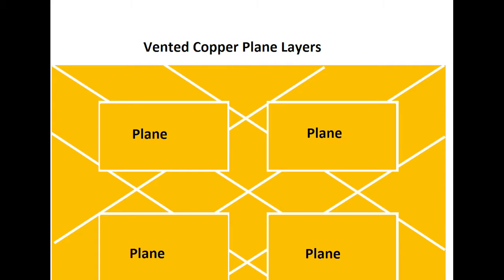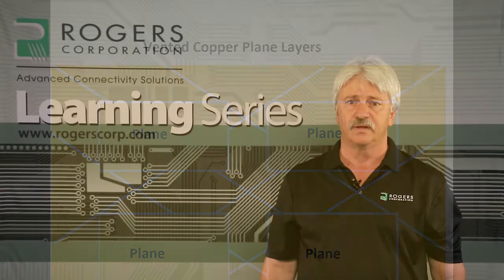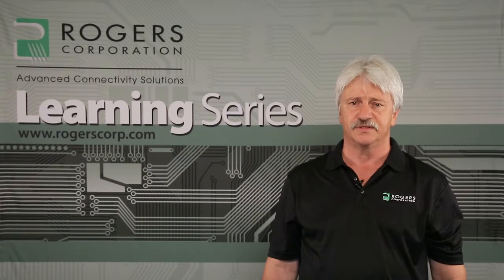Nearly solid copper patterns are not preferred for venting plane layers in RO4000 multilayer board constructions. In the case of plane layers, it is preferred to have 125 to 150 mil wide venting channels etched into the copper borders. Properly sized venting channels permit the evacuation of air during a short vacuum drawdown and are within the lateral flow capability of the RO4450 bond ply layers.